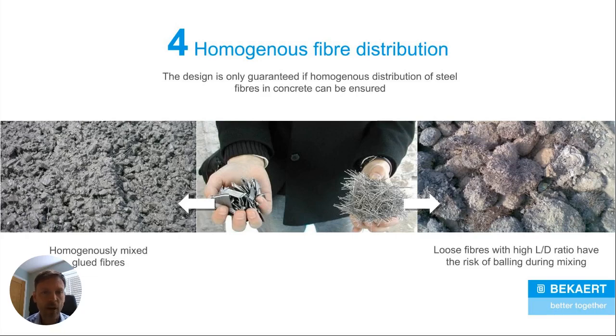The fourth thing, homogeneous fibre distribution. Now you can see on the photo in the center there, we have 2 examples of fibre addition. On the right hand side, what you see there is a high aspect ratio fibre that's been added to the concrete in loose format. And what you see on the left-hand side is the same fibre that's glued together in bundles. Now, one aspect of high aspect ratio fibres is that you get higher performance. The downside is that workability is decreased and it becomes more difficult to work with that fibre.